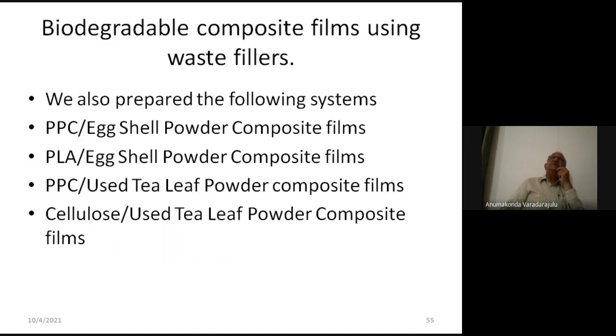But then we thought, why don't we use some waste materials as the fillers so that the cost of these composites can be brought down. So we used eggshell powder as the filler. We also used tea leaf powder. After brewing tea, we throw it away, but that can be dried and made into powder, and used as a low-cost filler. We used PPC and PLA as the matrix materials, and also cellulose. Let me show some of the systems we prepared in this direction.